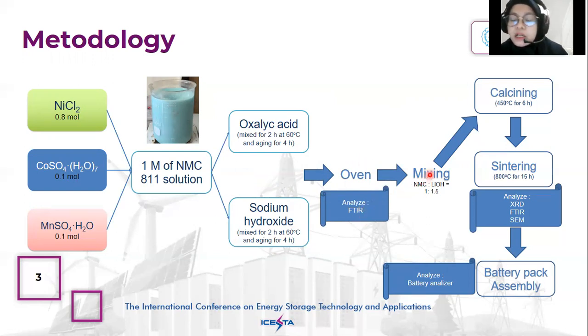The next process is that the material is mixed with lithium hydroxide with the ratio 1 to 1.05. After being mixed with lithium hydroxide, the two materials were calcined at 450 degrees for 6 hours in the furnace, followed by a sintering process at 800 degrees Celsius for 15 hours under flowing oxygen. After that, XRD, FTIR, and SEM analyses were carried out. The cathode is prepared by coating the slurry onto an aluminum foil, followed by drying in the oven. After the electrode was completely dry, cells were assembled by filling electrolyte in the glove box and tested in the battery analyzer.